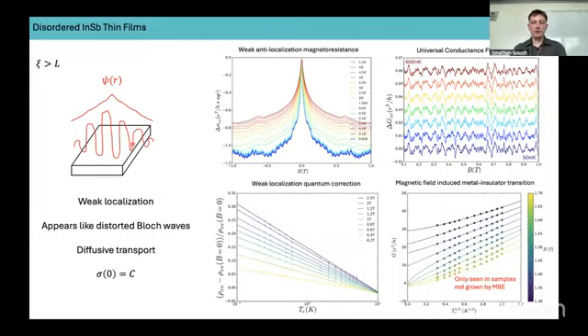Because we're in this weakly localized regime, we observe a lot of phase coherence effects, so the contribution due to this self-interference, which I mentioned before. One is a weak anti-localization magnetoresistance. Typically when you put a magnetic field on a weakly localized system, you destroy self-interference. All those looping terms are destroyed by the magnetic field, so you would get an enhancement in your conductivity. But because there's also a strong spin-orbit interaction in indium antimonide, this effect is flipped due to an additional pi phase shift associated with spin.